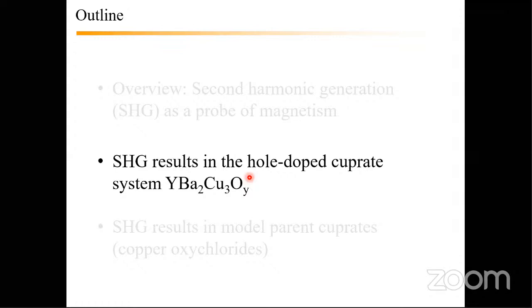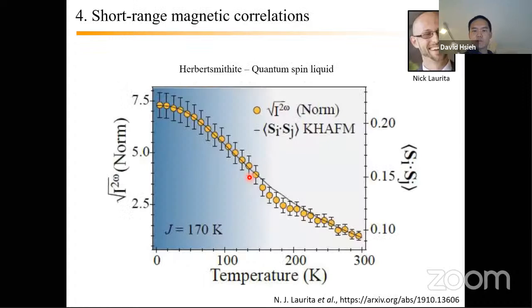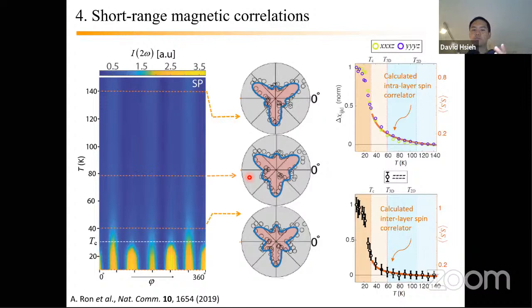Yeah, we can go as quantitative as... So maybe I'll say another word about this experiment. We can go as quantitative as saying, since there's no symmetry broken, what we do is look at all the totally symmetric distortions of the crystal and how those distortions might affect the various tensor elements in your response. So we can go as quantitative as to say that these tensors turning on corresponds to this type of totally symmetric distortion, this A1G mode or something. But correlation lengths, I would say, are currently beyond our capability.